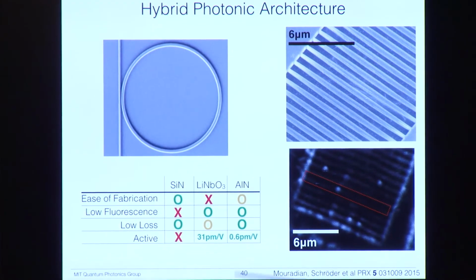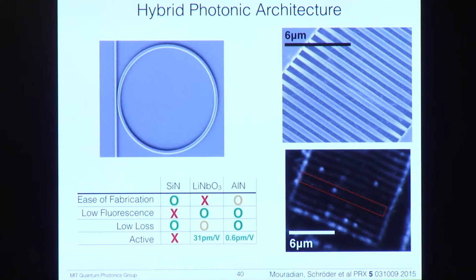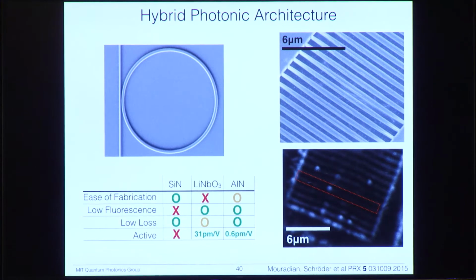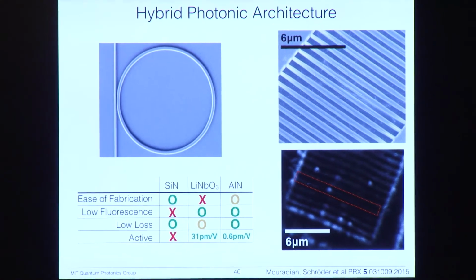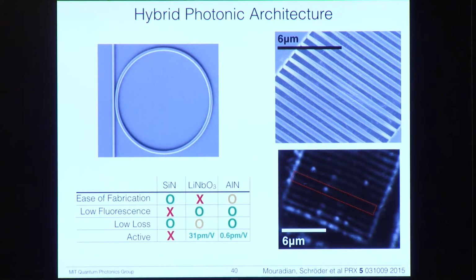And you'd also like it to be active, so you can do a lot of this routing on chip. So you can say, okay, now I want to connect nodes 1 and 3, and after I create entanglement between those nodes, I'd like to connect nodes 1 and 4, for instance. And both lithium niobate and aluminum nitride are active. So now in the lab, they're starting to work with those two materials. But the results I'll show here are with silicon nitride.